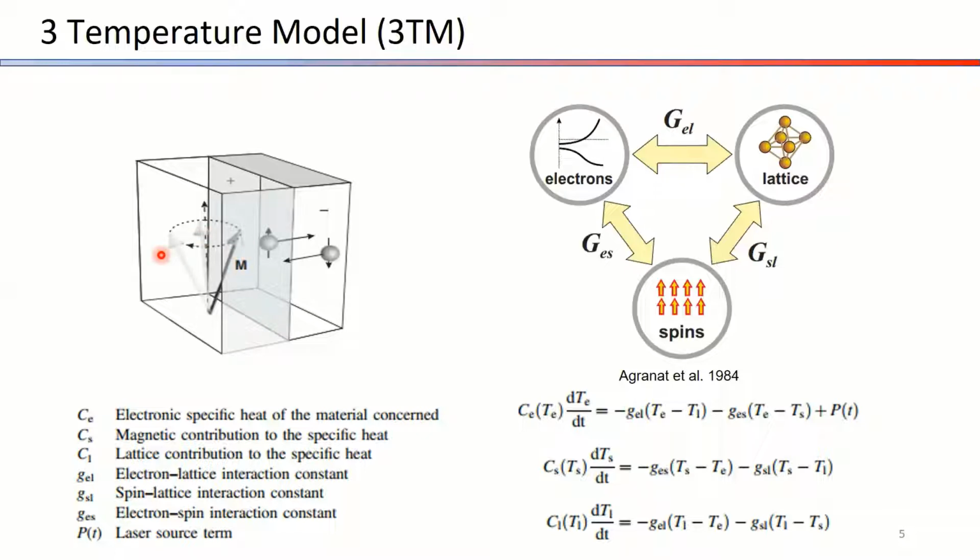And one of the ways to create pure spin current is by spin pumping in materials with strong spin-orbit coupling. So this one, spin pumping: after we hit the sample with the femtosecond laser, the ferromagnetic layer will precess, and then it will transfer the spin angular momentum across the interface to a non-magnetic metal here. So they will generate the spin current.